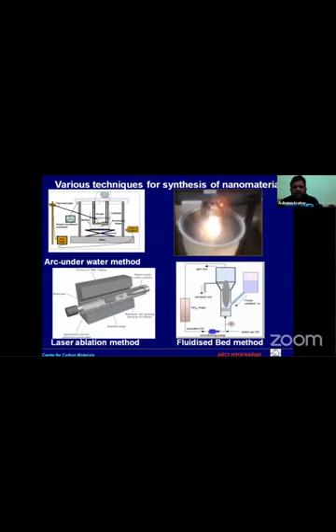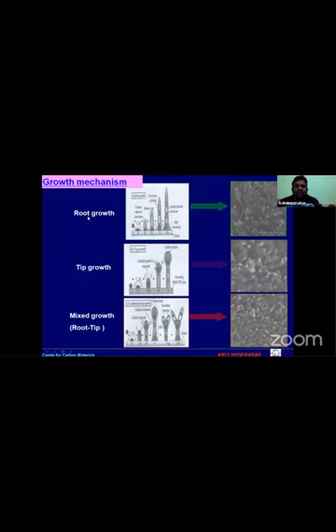This is arc underwater. The arcing of graphite electrodes is done underwater, and one can grow the nanotubes. Even laser ablation, this is the laser ablation method, and this is a fluidized bed reactor where the carbon source and the catalyst are fed, and one can get carbon nanotubes. Now, depending on the growth mechanism, it can be root growth, tip growth, or mixed growth, where you require a catalyst to grow these nanotubes, a transition metal like cobalt, iron, or nickel. So either these particles will be on the top or on the base, depending on your parameters. One can get different types.